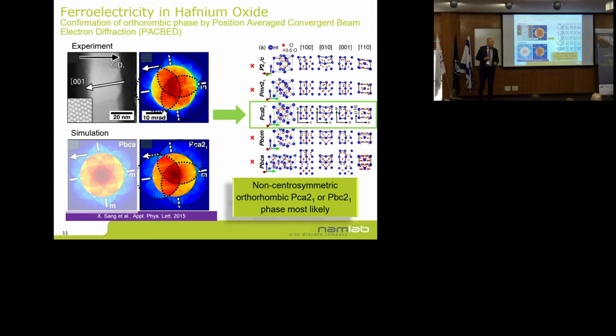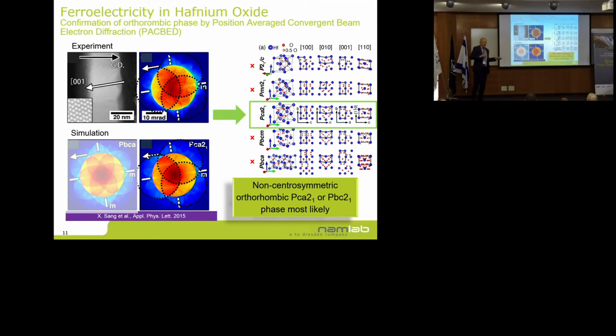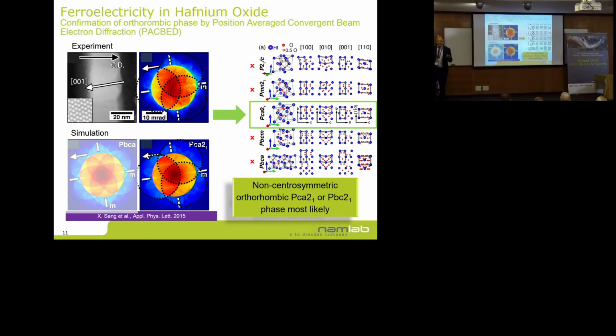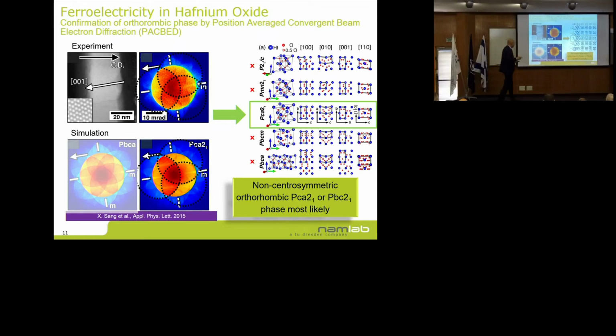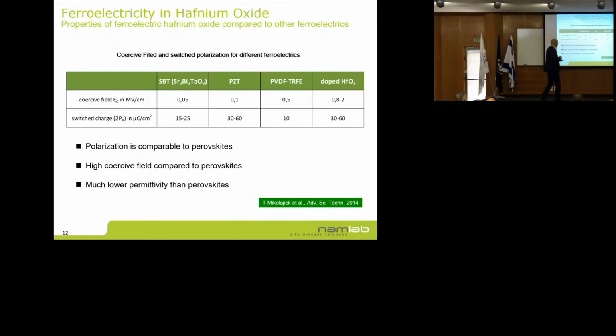But people from NC State just 2 years ago did some very nice work on position averaged convergent beam electron diffraction, and they could really show that the crystals that we get are non-centrosymmetric and that they only match to the Pca2_1 phase, the orthorhombic phase.